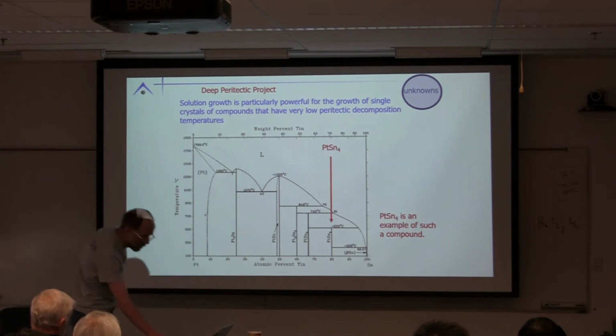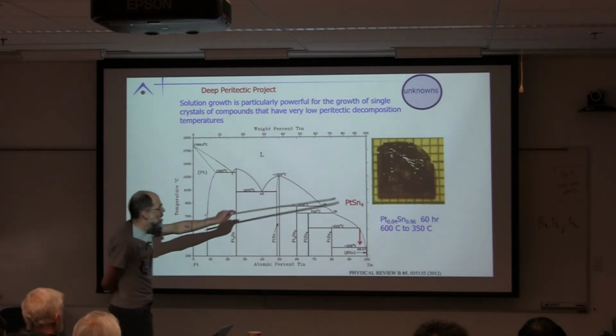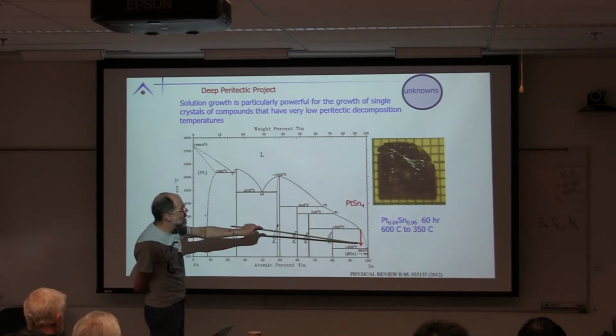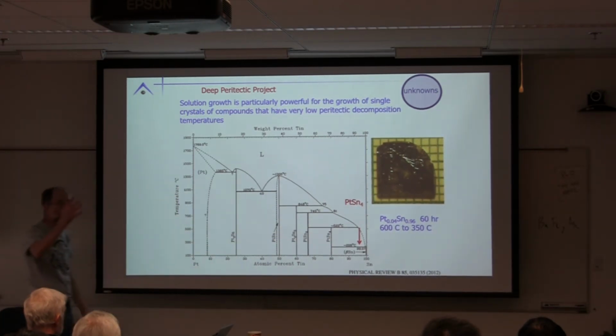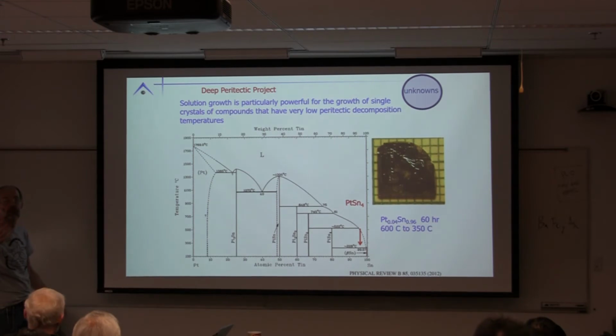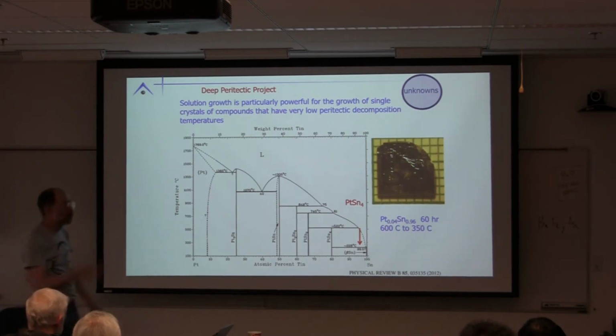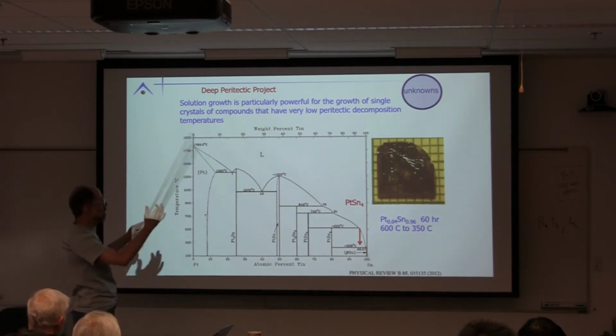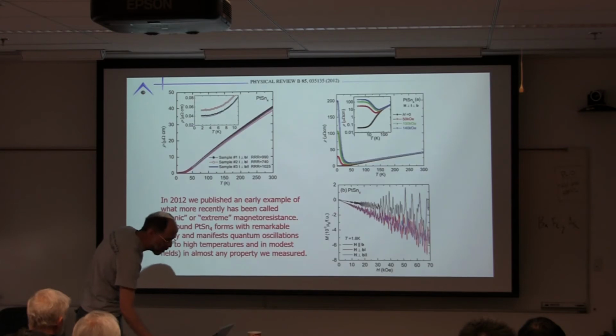Platinum tin 4. Lovely. We can grow this out of a vast excess of tin. We get beautiful single crystals using these printed alumina crucibles that we've developed. That is really important because you need sort of biggish holes to have the tin decant, because it has surface tension at these temperatures. Lovely. What do we do with it?